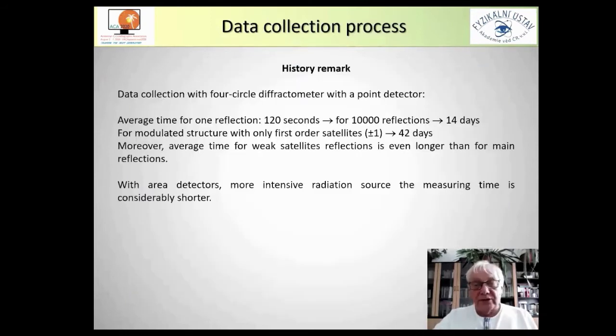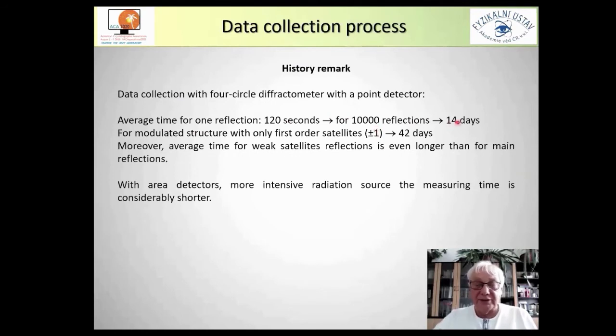Just a short history remark. Data collection with a four-circle diffractometer with a point detector was extremely time-consuming. Average time for one reflection was about 120 seconds, and for 10,000 reflections it was necessary to spend 14 days on the diffractometer. For a modulated structure with only first order satellites, this changed from 14 to 42 days, but only if the satellites were strong enough.